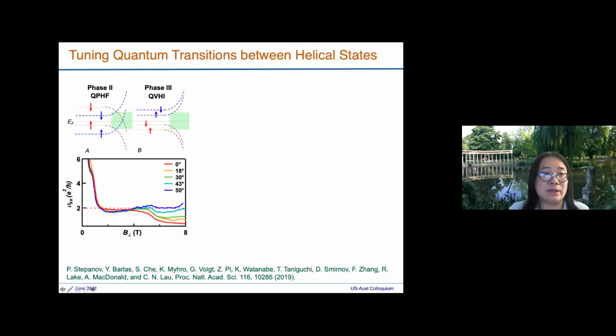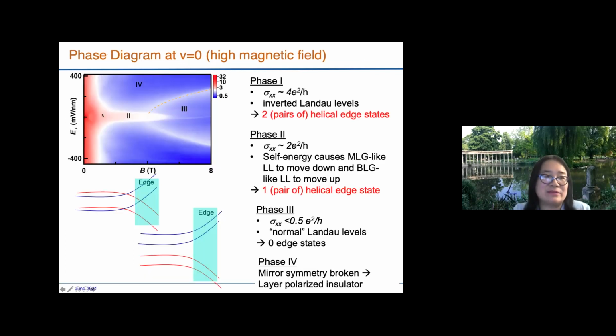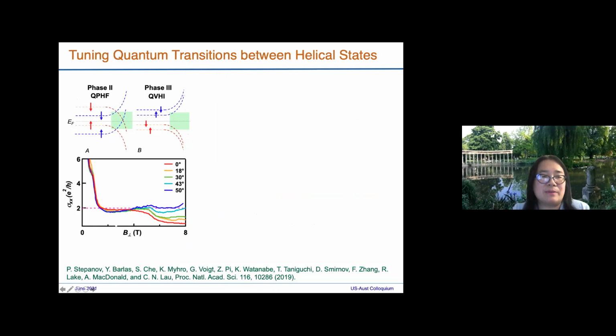Okay, so it also turns out that if we stay at phase 3, which is the insulator, and we keep a constant perpendicular field while adding an in-plane field, then, for phase 2 and phase 3, the red one is at zero in-plane field and you can see it's insulating. As we add more and more in-plane field, you can see that we recover the 2 e squared over h, two times the conductance quantum, in conductivity. This shows that the Zeeman energy restored the crossing when it was split, and Zeeman energy caused them to cross again, and that gives us this phase diagram.